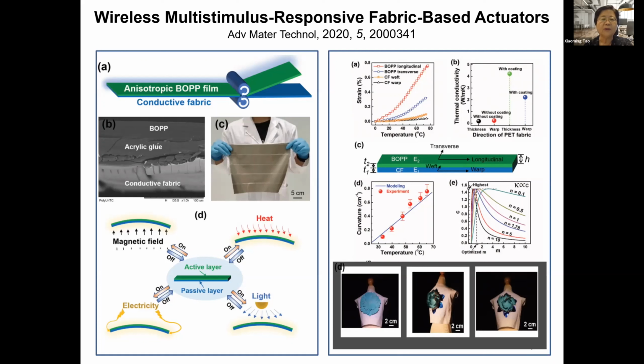Now, this is using a bimorph structure with an anisotropic biaxially-oriented PP (BOPP) film laminated on very thin conductive fabrics. And this manufacturing process is quite simple and straightforward. And this fabric can be made into several devices.